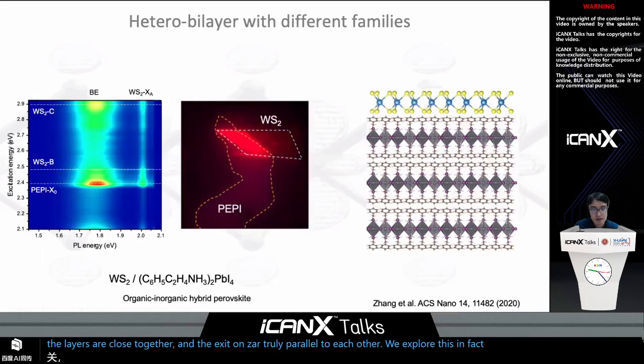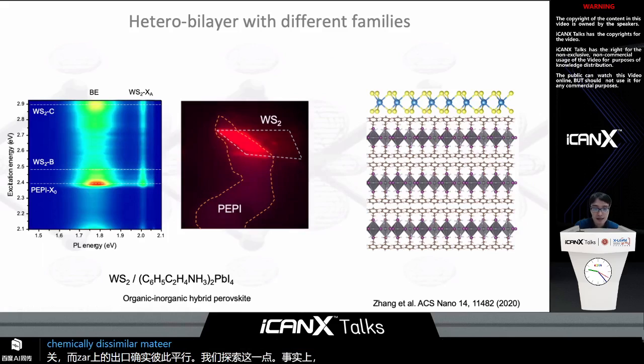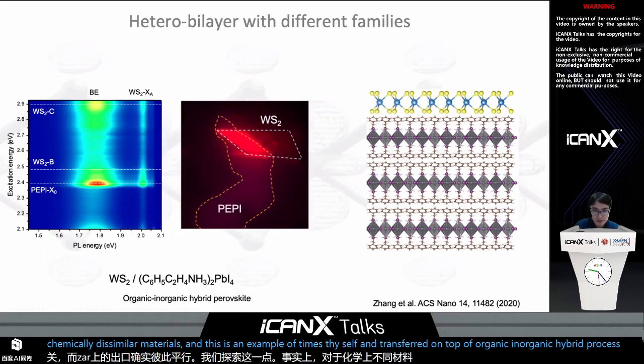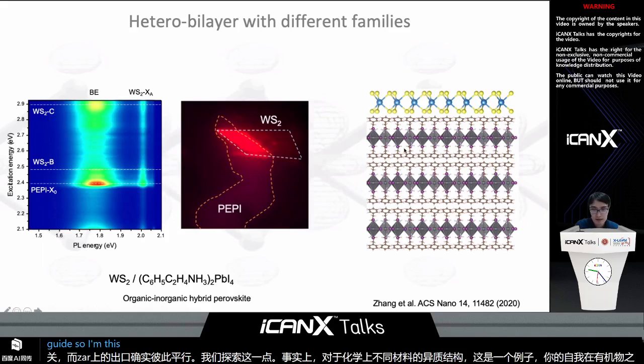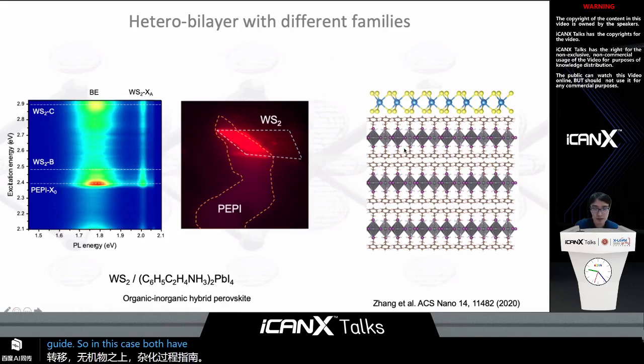We explored this effect for heterostructures of chemically dissimilar materials. This is an example of tungsten disulfide transferred on top of an organic-inorganic hybrid perovskite. So in this case, both have a quasi-two-dimensional structure.